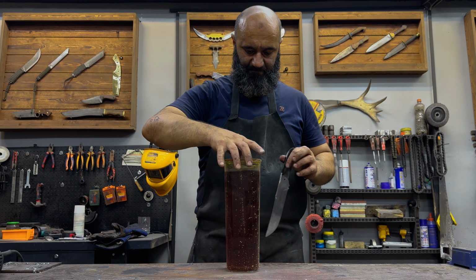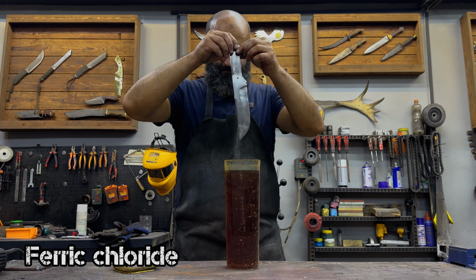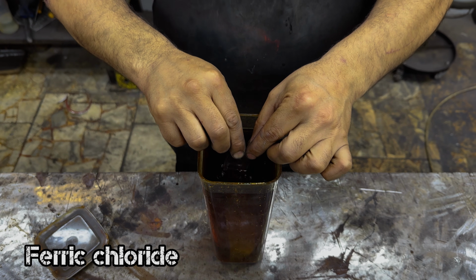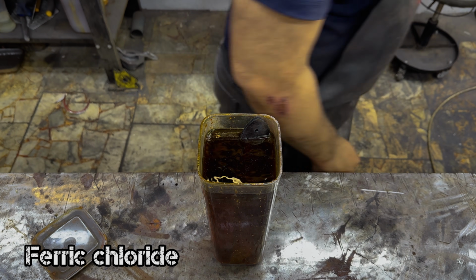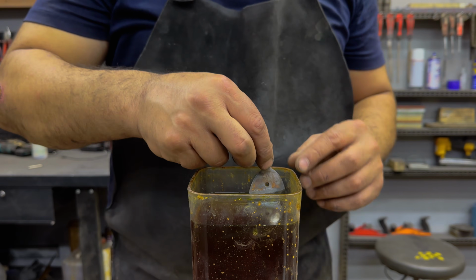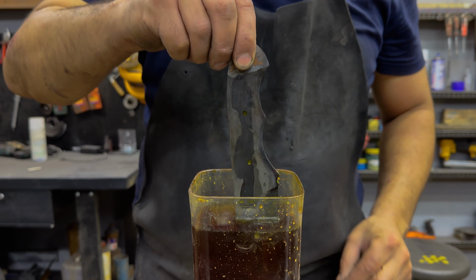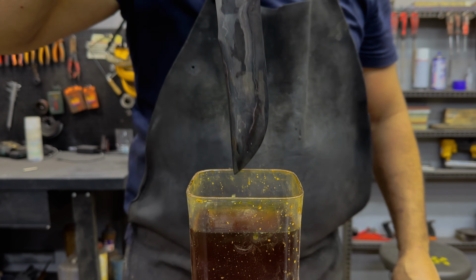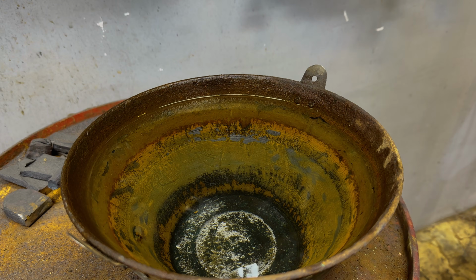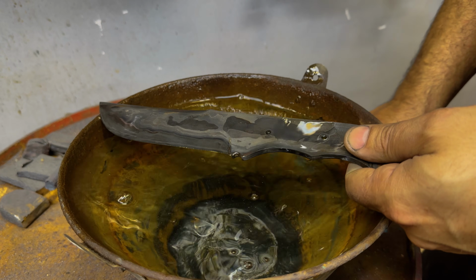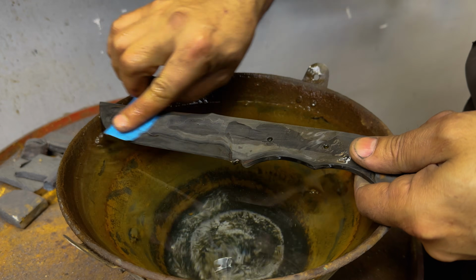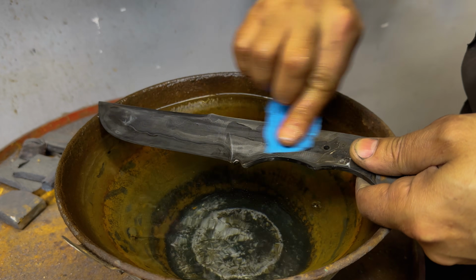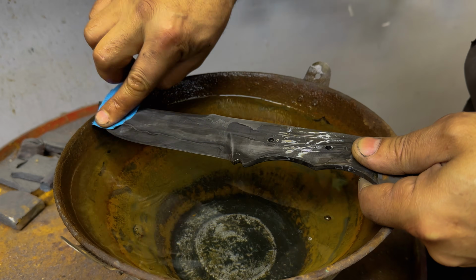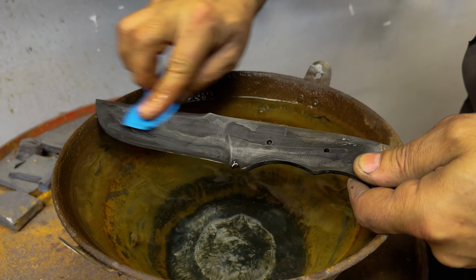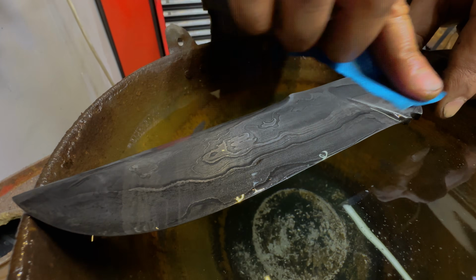Now for the moment of truth. We take our freshly prepped blade and submerge it completely into a container of dark ferric chloride acid. This chemical bath is where the real magic happens. We drop it into a bowl of water and start scrubbing the face with fine sandpaper. Look at that contrast starting to pop out under the water. The acid eats away the softer steel layers faster, leaving the harder lines behind.